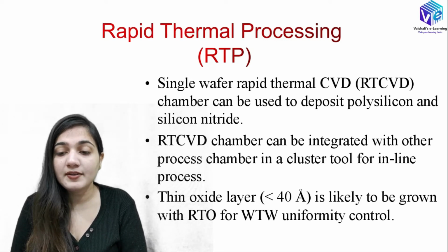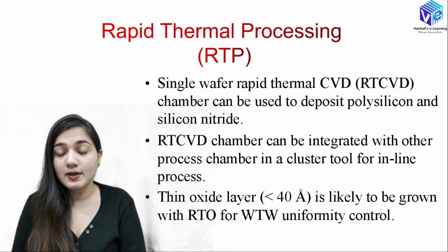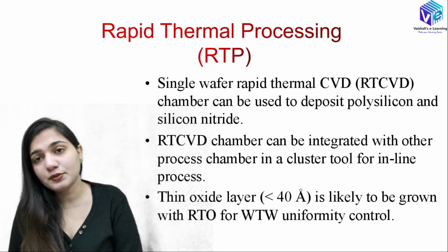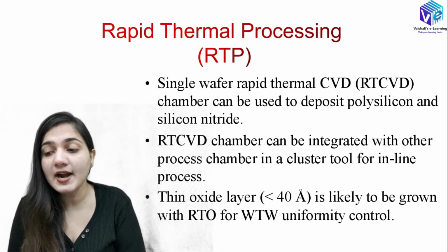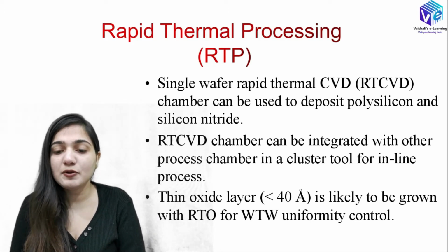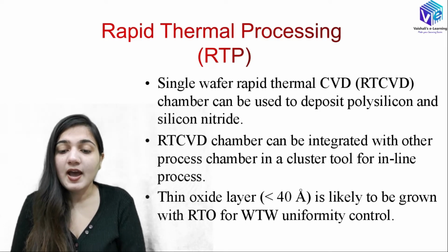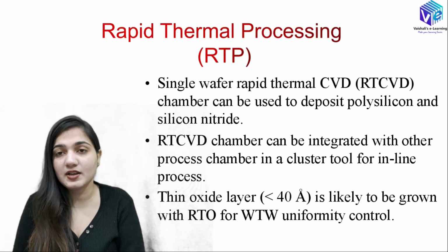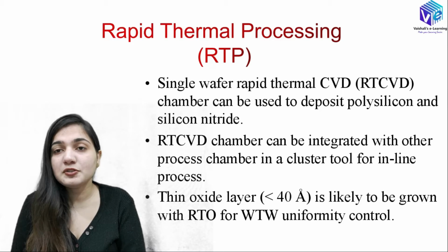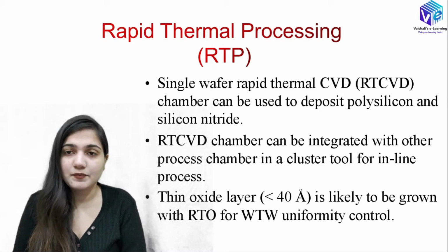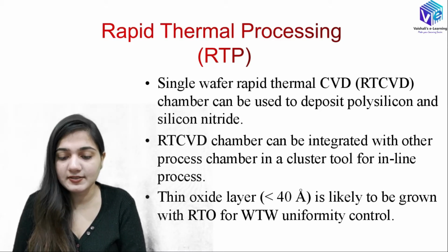Here we also have single wafer rapid thermal chemical vapor deposition. Instead of annealing, we can do the CVD process as well, which is called the RT-CVD process. Here we use RT-CVD chambers to deposit polysilicon as well as silicon nitride. RT-CVD chambers can be integrated with other process chambers in the cluster tool for inline processing, so that I don't need to do this processing outside this system. We will have the inline integrated system only.